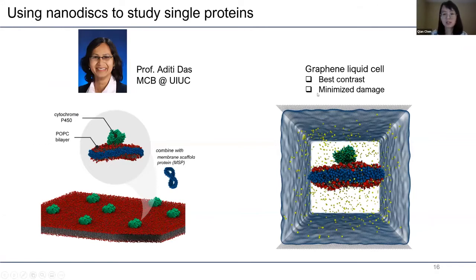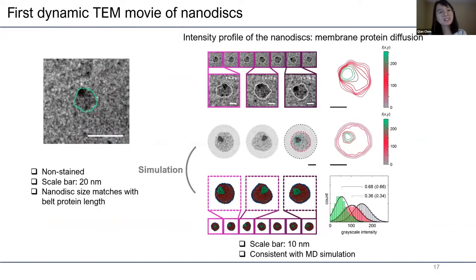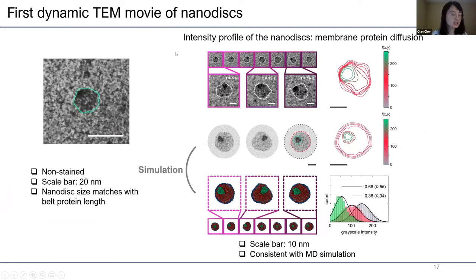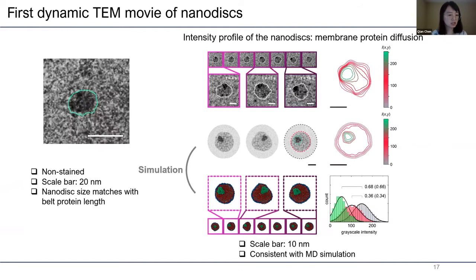We use the graphene crystal to do the imaging, which gives us the best contrast, and can also minimize electron beam damage. I should mention, this is an extremely difficult experiment. I still remember one night at 11 p.m. when Johnny sent me this email with this movie attached, the first ever movie of a dynamic nanodisc in solution. In this movie, the scale bar is 20 nanometers. The system is not restrained.